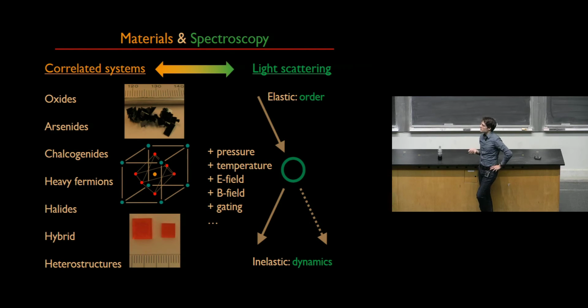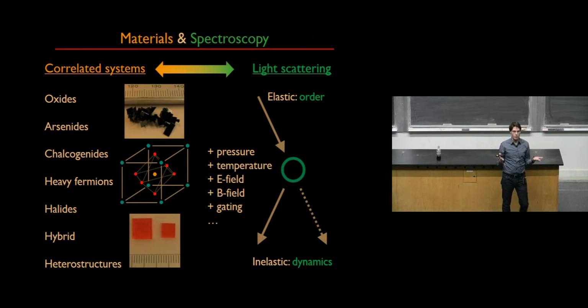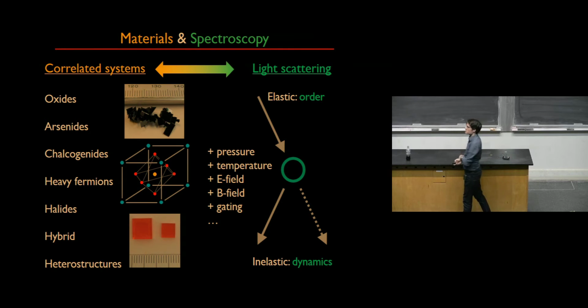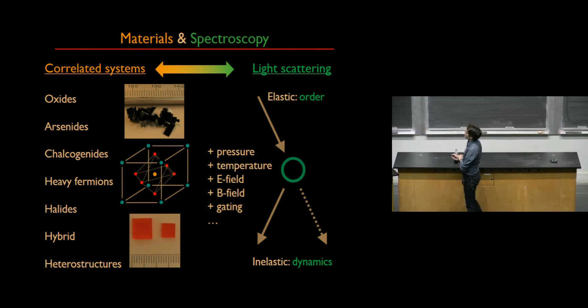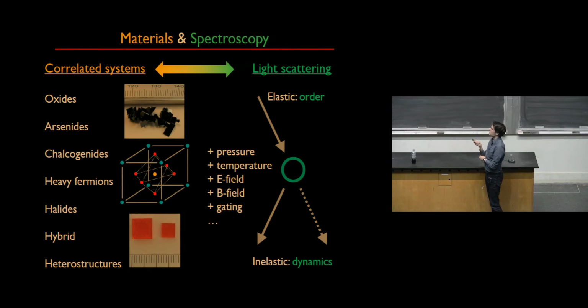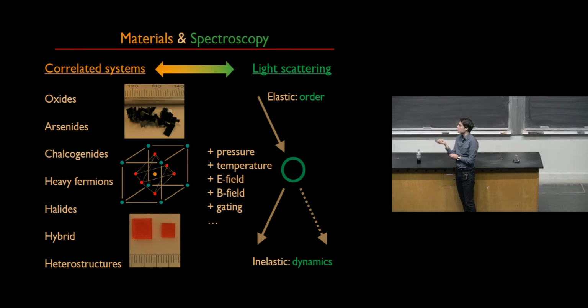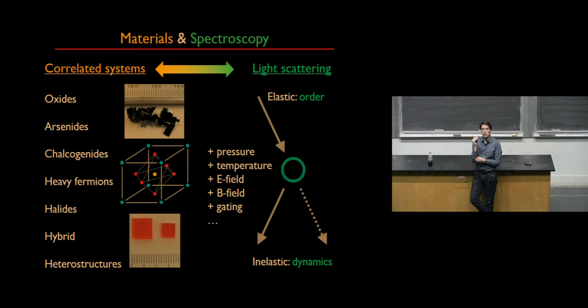And as I mentioned in the beginning, we're going to do synthesis, spectroscopy, and scattering on a bunch of different materials platforms, going from oxides, transition metal oxides, arsenides, chalcogenides, a bunch of quantum materials, so all materials that have, one way or another, strong electronic correlations and exotic electronic phases. And then we use light scattering. So this could be optical, like Raman scattering, or X-ray. And we do both elastic scattering to look at static orders, but also inelastic scattering. So when you not only transfer momentum to the sample, but you also transfer energy, to look for the momentum-energy structure of excitations in your material.